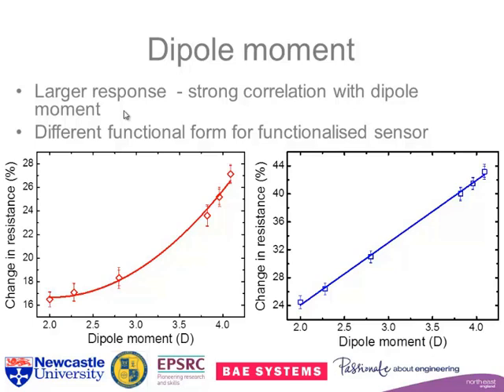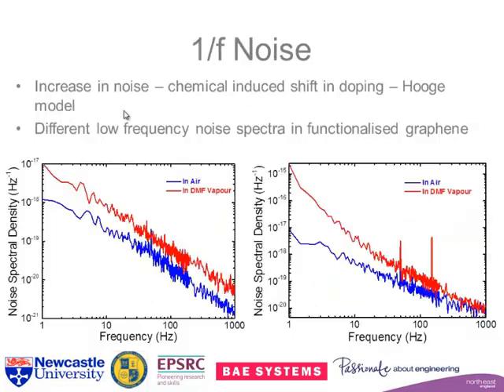This is the same data taken on the same day for functionalized material. Notice the response here at 44% is higher than that at 28. But we see the same trend. The dipole moment increases, the response from our sensor increases. This is because when we put a molecule on the top, it changes the amount of charge in the graphene, and so it changes the resistance, and that's our idea of how the thing works.